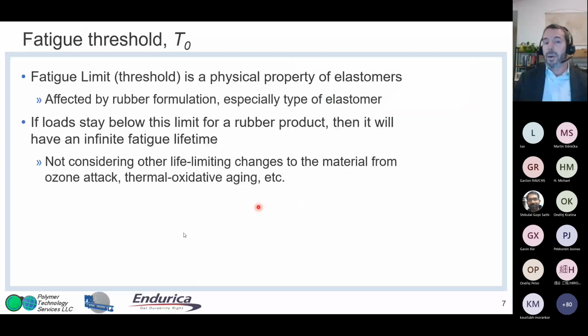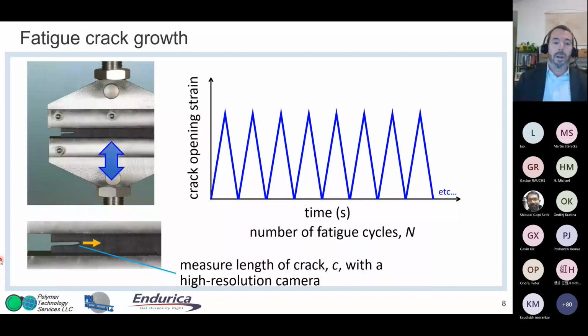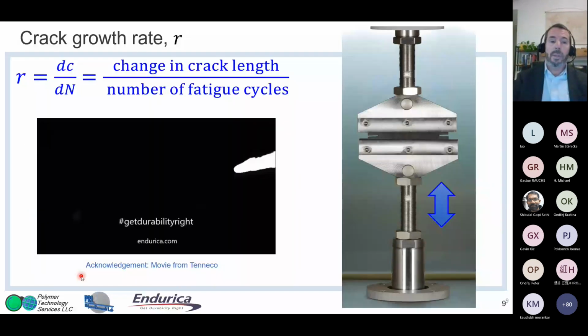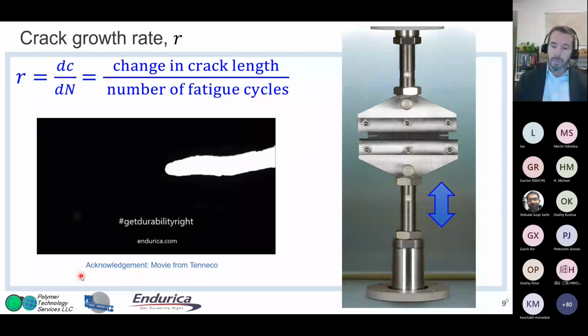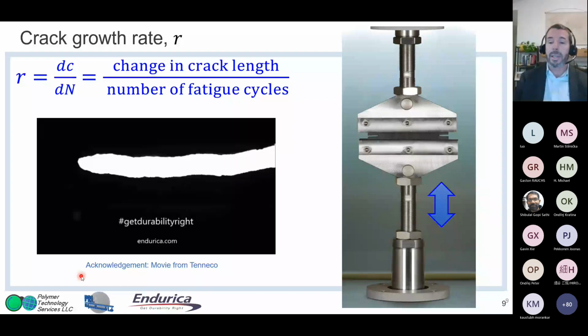So let me just briefly cover fatigue crack growth so you can understand the whole picture. Typically fatigue crack growth, we take some specimen. Oftentimes it's this so-called planar tension specimen with an edge crack, and then that crack is open and closed. I show here just a simple kind of sawtooth strain function versus time, but it could be a sine wave or it could be a pulse. So I'm just showing this as an example. And then you would watch the crack grow with a high resolution camera. And so you measure a crack growth rate, how fast that crack grows for a certain number of fatigue cycles where the crack is open and closed, and then characterize that crack growth rate at different conditions.